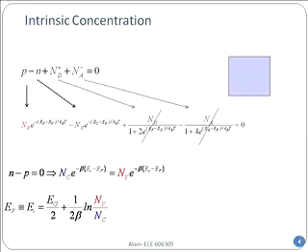Remember, this is the intrinsic semiconductor. Of course, the more complicated expression will reduce to this very simple formula when I remove my acceptors and donors. No problem here. And once you have EF, you could easily calculate the value for N, which is now the intrinsic carrier concentration, 10 to the power 10 per centimeter cube, and correspondingly also the value of holes.